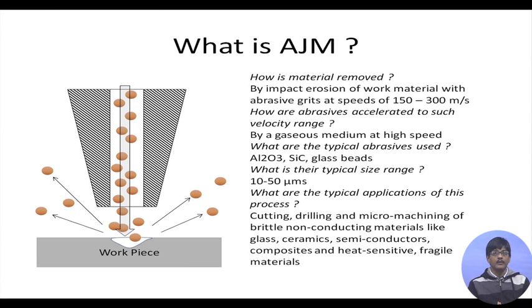So, let us have a quick look at the method. How is material removed? By impact erosion of work material with abrasive grits at speeds of 150 to 300 meters per second. Some people even consider it to be 100 to 300 meters per second. How are abrasive particles accelerated to this velocity range? This is done by a gaseous medium at high speed. What are the typical abrasives used? The typical abrasives used are aluminum oxide, silicon carbide, glass beads, etc. What is the typical size range? They are in the size range of 10 to 50 microns.